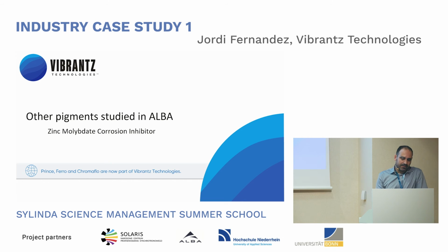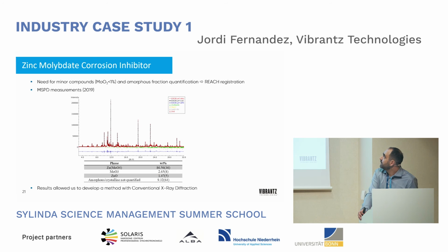We finished this study in 2017, and as we had a very good collaboration with ALBA staff, we continued studying another kind of pigments, the anticorrosive pigments, in this case the zinc molybdate corrosion inhibitor. In this case, the study was shorter, but it was focused on the REACH registration of this pigment. The zinc molybdate, to be registered in the ECHA for its distribution in Europe, needs to be a